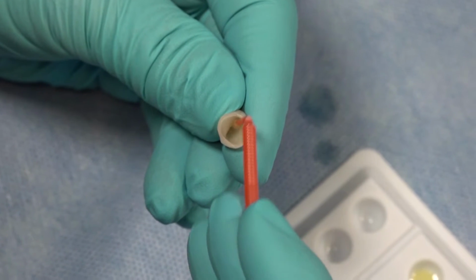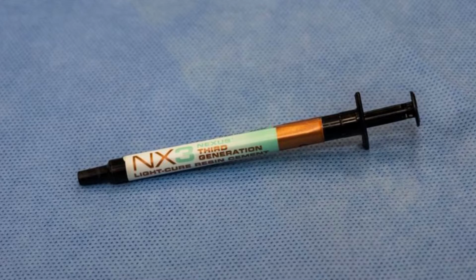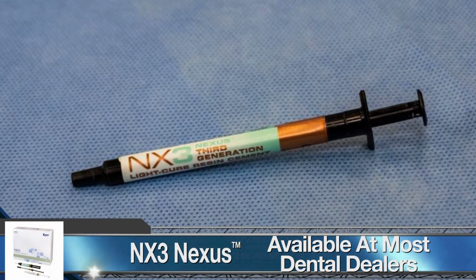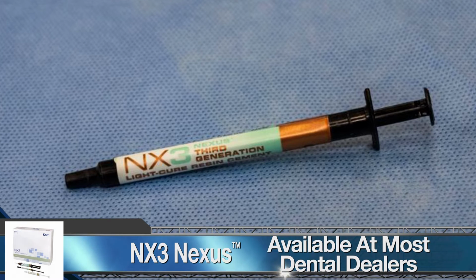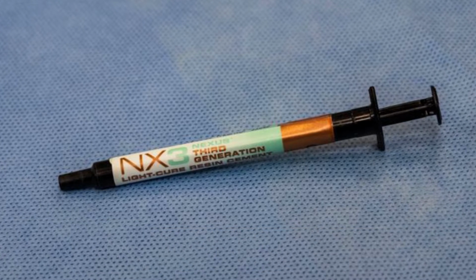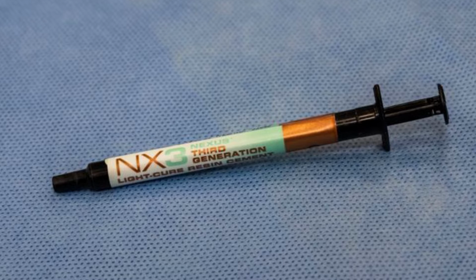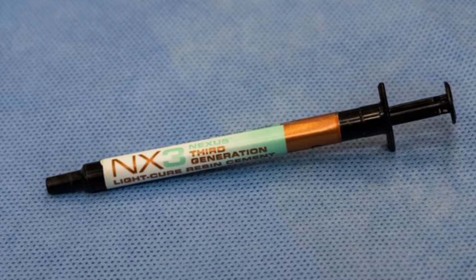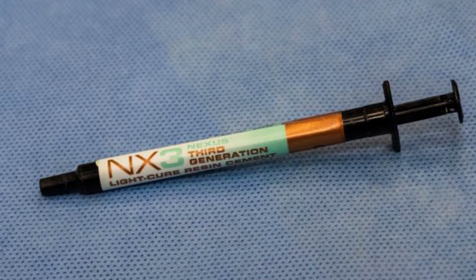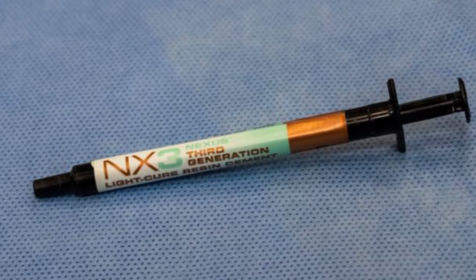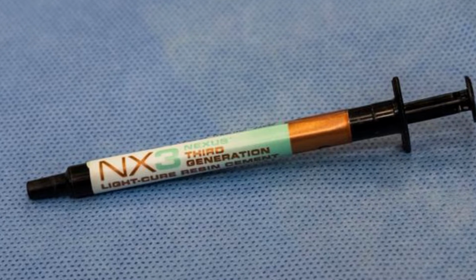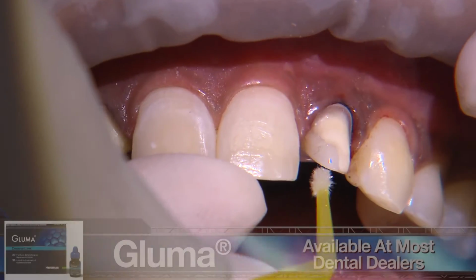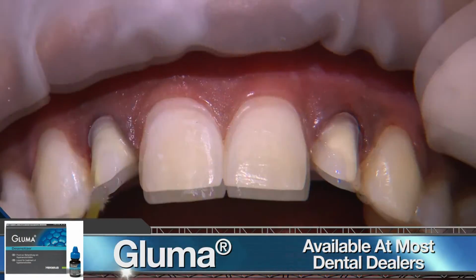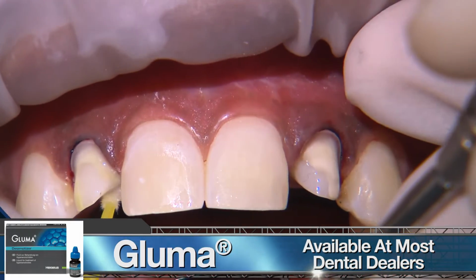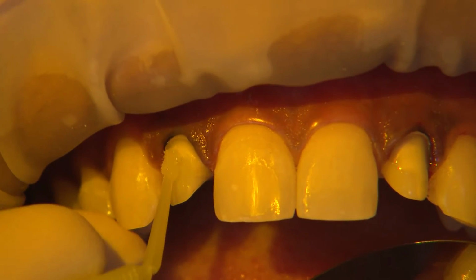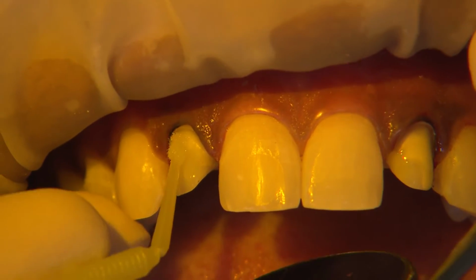While the preps are retentive enough to use a conventional cement such as a resin-modified glass ionomer, I recommend using an adhesive resin cement with more translucent restorative materials like BruxZir Esthetic in the anterior. The opaque white nature of RMGIs could potentially show through thin restorations and affect light transmission through the tooth, resulting in darker soft tissue. To disinfect the preps, I apply a very thin coat of Gluma, carefully avoiding the soft tissue. Any excess can be removed with a high-speed suction or a dry microbrush.